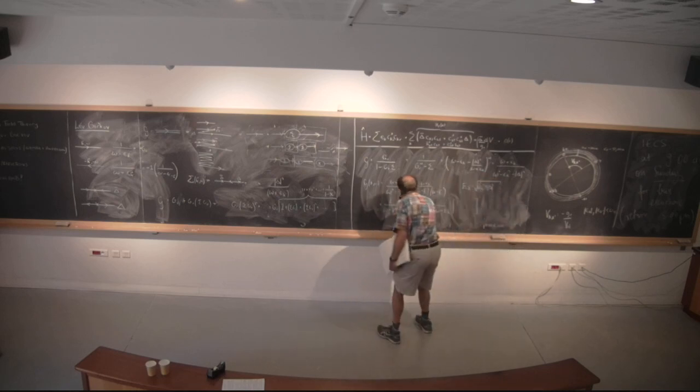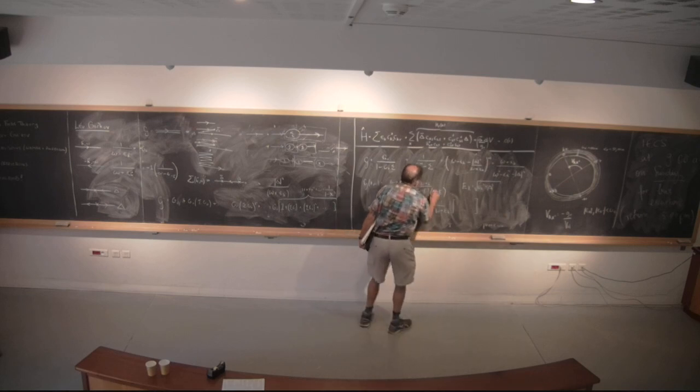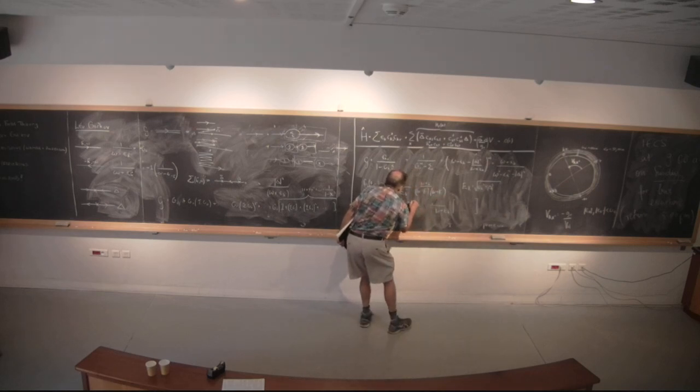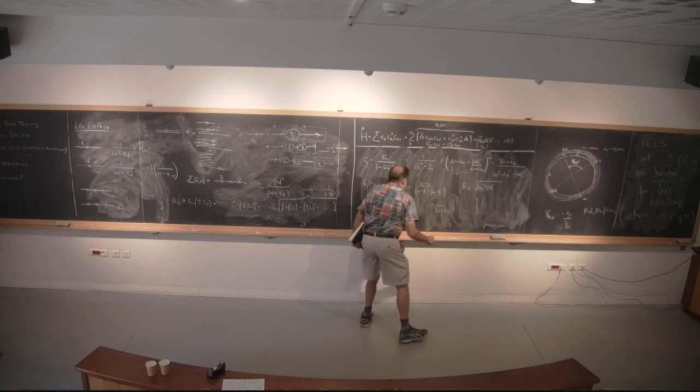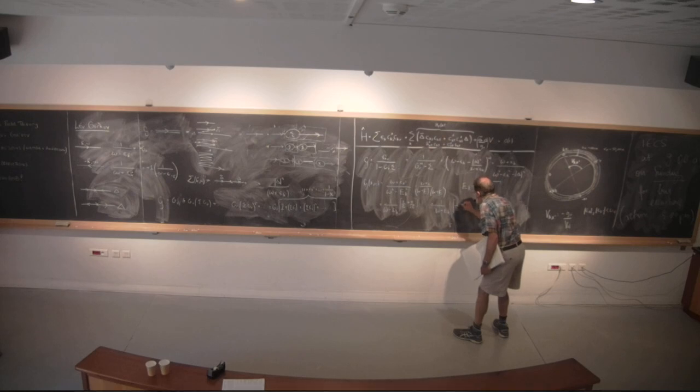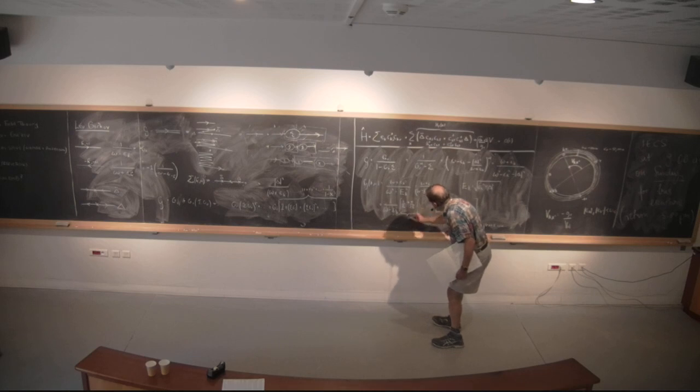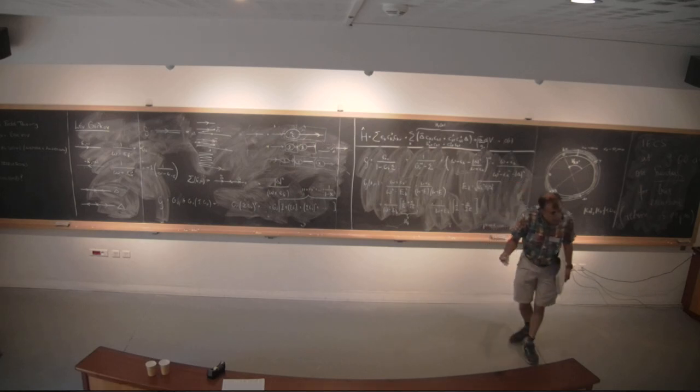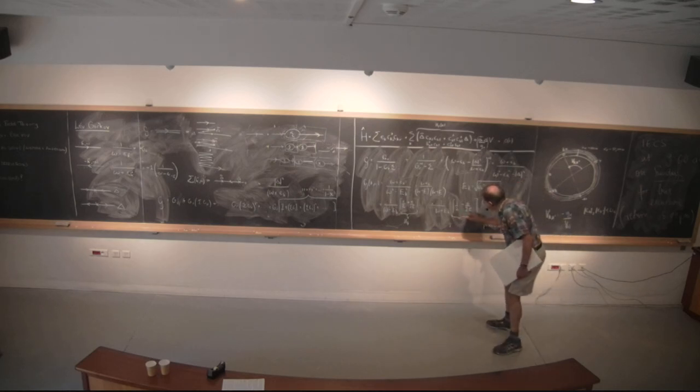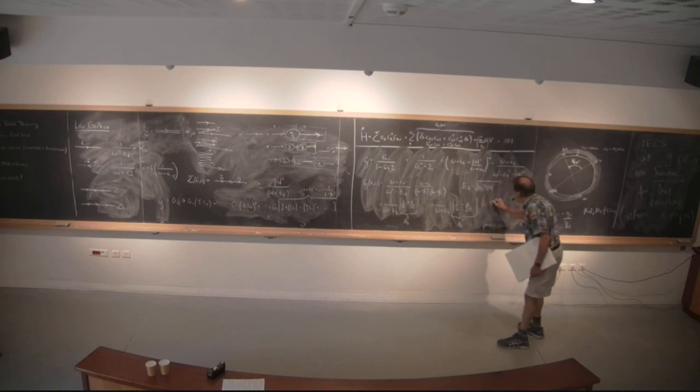And so you can write this term here as a half, big E over 2 big E plus epsilon over 2E. And you can write this term as a half minus epsilon over 2E. And historically, this is called u squared, because this is nothing more than the u that appears in the BCS ground state, and this is vk squared here. And so this thing can be written as uk squared over omega minus E of k plus vk squared over omega plus E of k.